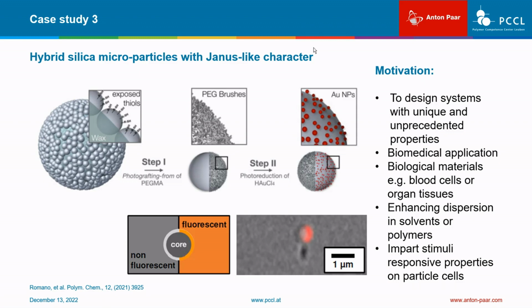They have received tremendous interest due to their potential to design systems with unique properties. The particles with Janus-like properties were synthesized by first masking the grafted silica particles through a wax-water Pickering emulsion, followed by selective UV irradiation of the unmasked particle domain. The formed carboxylic acid moieties were then used for the covalent attachment of a fluorescent biomolecule. With the Zeta potential and XPS, we confirmed the changes in the chemical surface composition of the silica particles during all the modification processes.